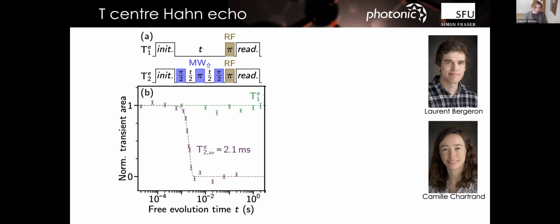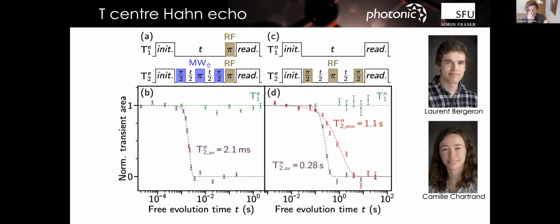While having that spin access, as an ensemble, we took a look at it, and in our first go, initialized the electron and the nuclear spins and showed that they have the expected performance you would get for a simple Hahn echo of the electron and the nuclear spin. Again, T1s so long that you don't bother measuring them, and T2s definitely limited by our home built magnet system, which could in principle be dynamically decoupled away, and which was what gave rise to those astonishing 3-hour coherence times in phosphorus. So we're not worried about the spin performance. We're quite happy with it.